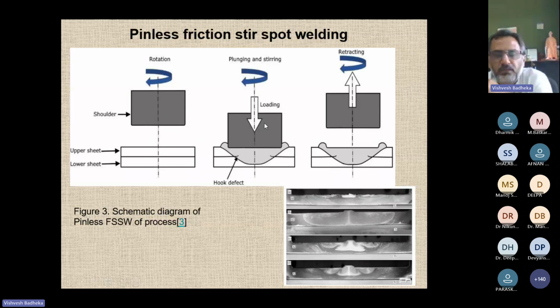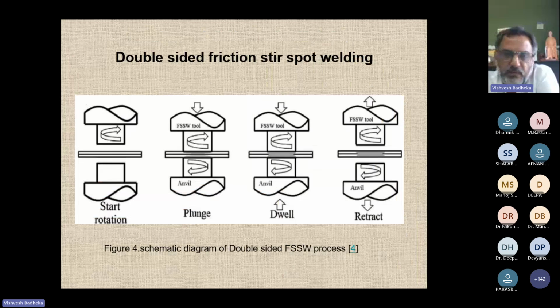Only the shoulder is there to deform the material, and you can see there is a large deformation, right? The deformation is very high, right? Because you are deforming not with the pin but with the shoulder, and you can certainly avoid the exit hole, but the overall deformation is very large at the joint location. So this is called pinless friction stir spot welding. So the earlier one was refill friction stir spot welding. And before that, what we discussed is conventional friction stir spot welding.